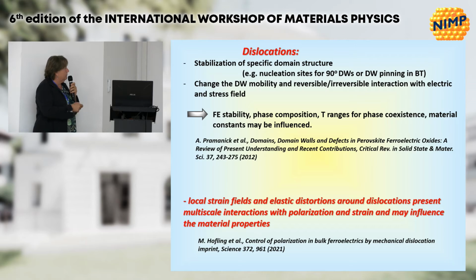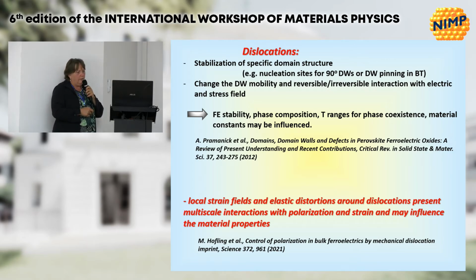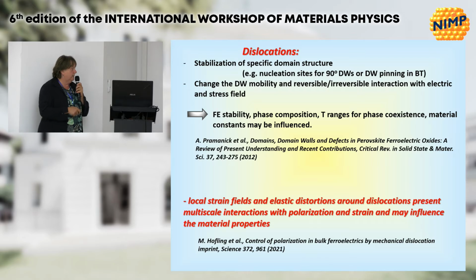So at the end, by looking at some data in the literature, dislocations are the origin of phase superposition. Somehow, by creating this internal stress, they stabilize the multiphase, or they stabilize the orthorhombic state in dense materials. They can be to some extent released when the material is porous, and they may be responsible for some enhanced properties, and if one understands how to control or to promote them, maybe they will obtain, like we found here by chance, I would say, higher permittivity, higher polarization than in the classical tetragonal barium titanate ceramics.